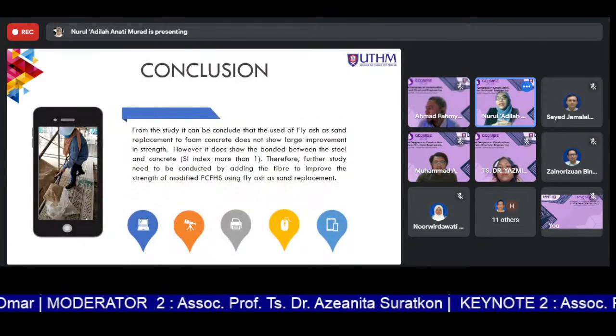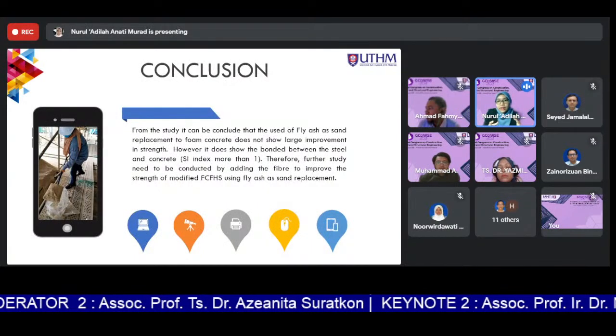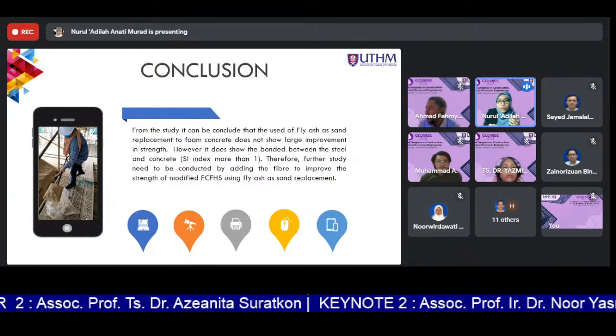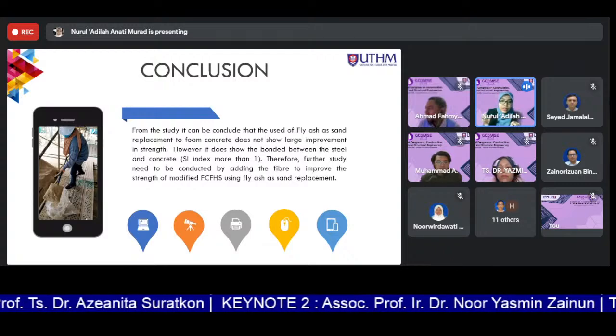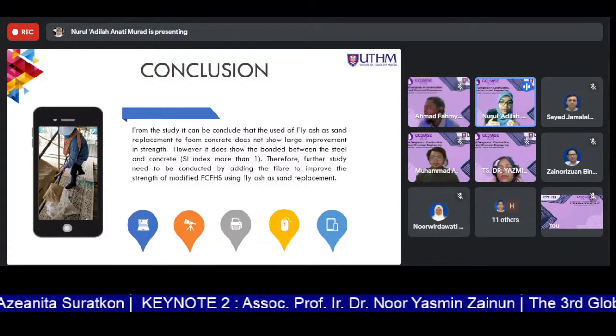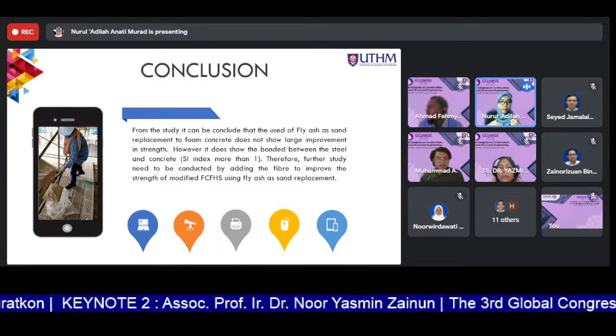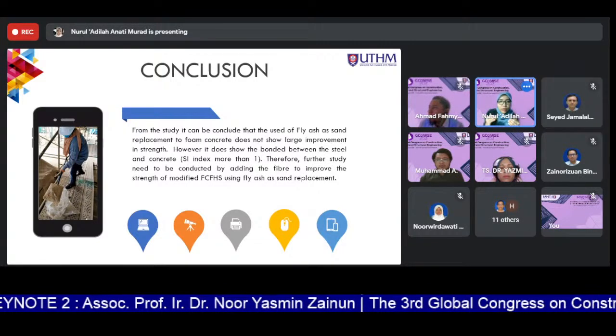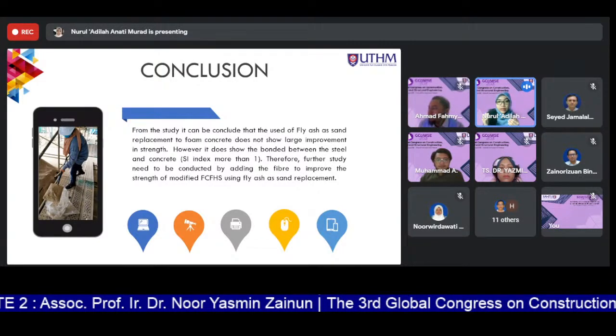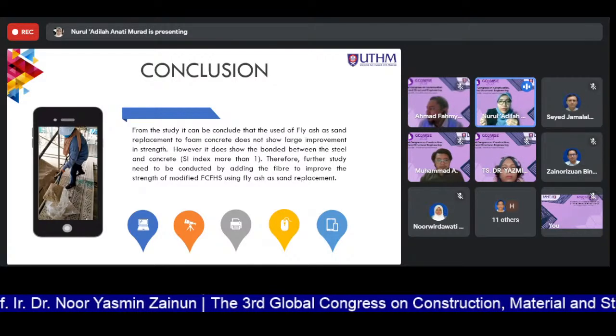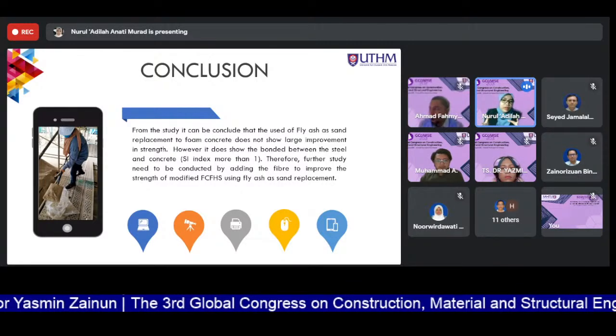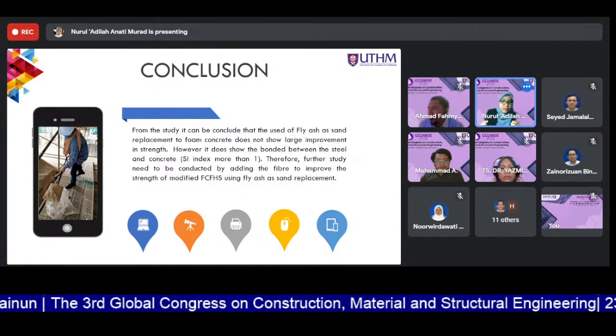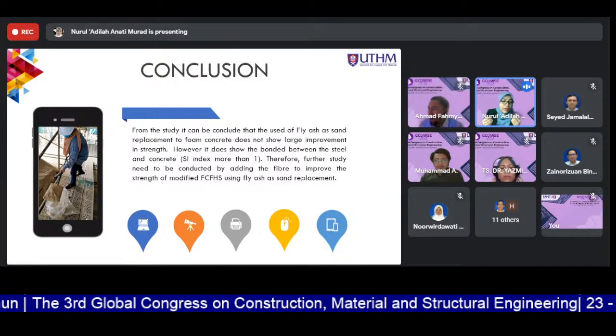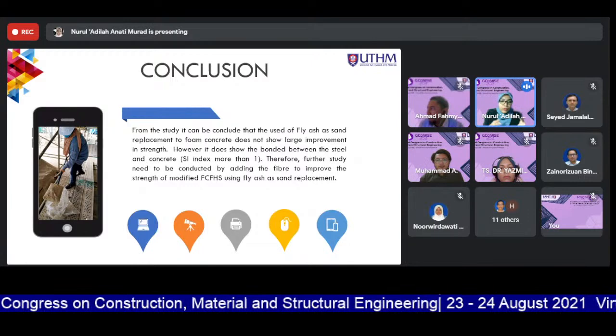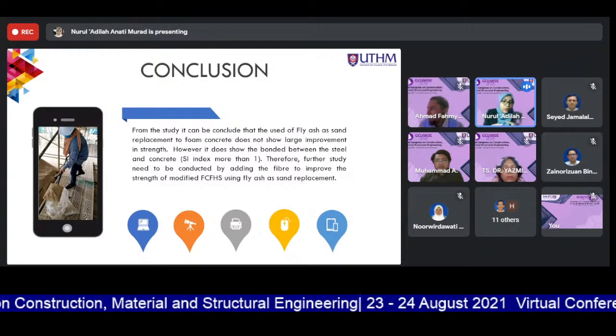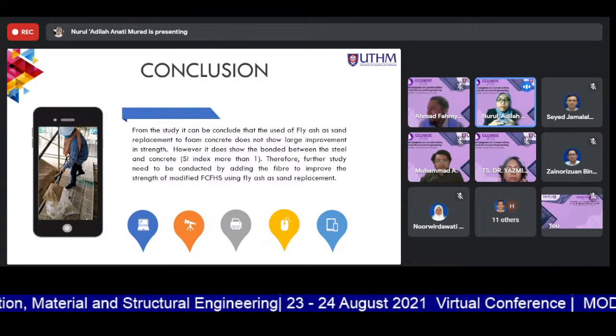And from the study, it can be concluded that the use of fly ash as sand replacement to foam concrete does not show large improvement in strength. However, it does show the bond between the steel and concrete, with a strength index of more than 1. Therefore, a recommendation for further study is adding fiber to improve the strength of modified foam concrete using fly ash as a replacement.